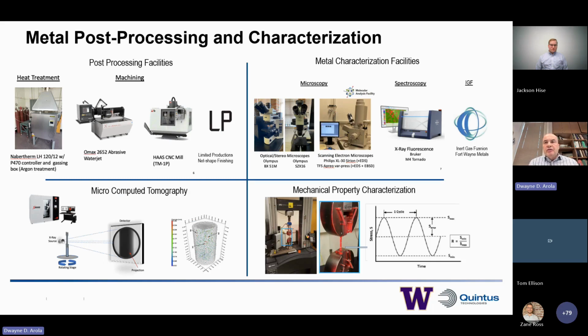Each of the partners involved in the program performs their builds and then sends that metal to the University of Washington. Post-processing involves potentially a heat treatment process at the university, utilizing an argon environment for a low temperature anneal. What we'd be doing then also is support removal and then, of course, net shape machining, and then recruiting the use of a solution partner to do the longitudinal grinding that's required for the fatigue studies, which I'll point out in a little bit.